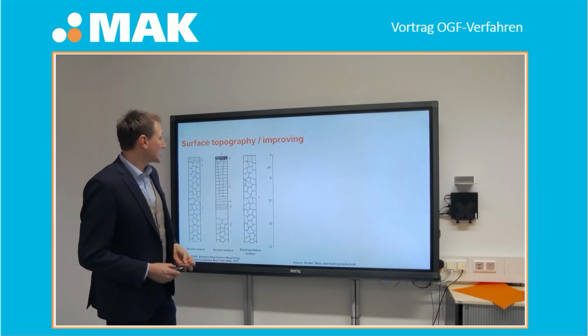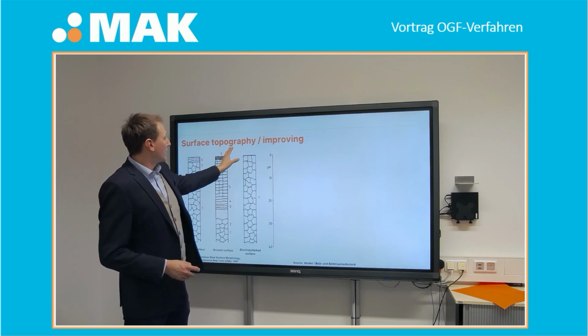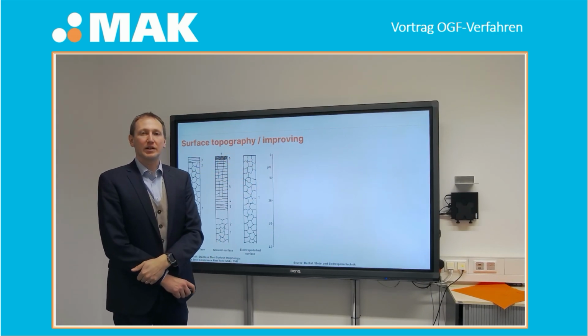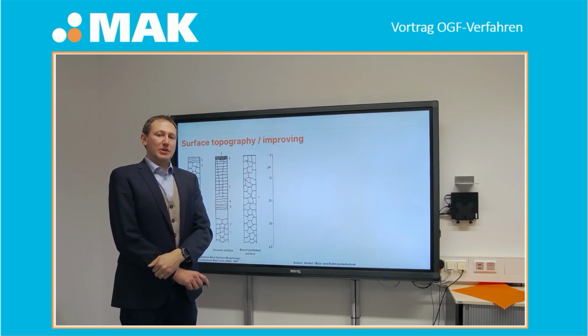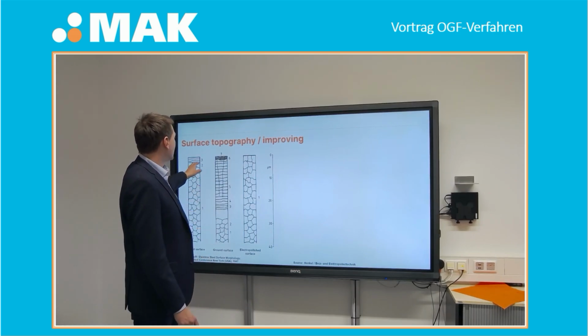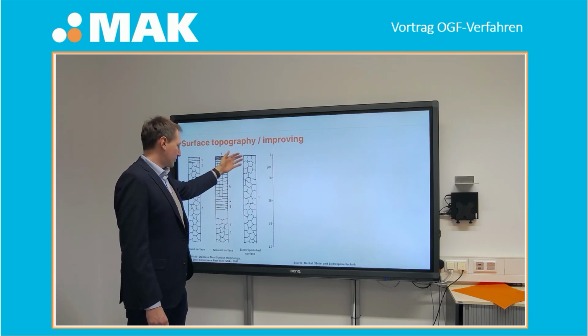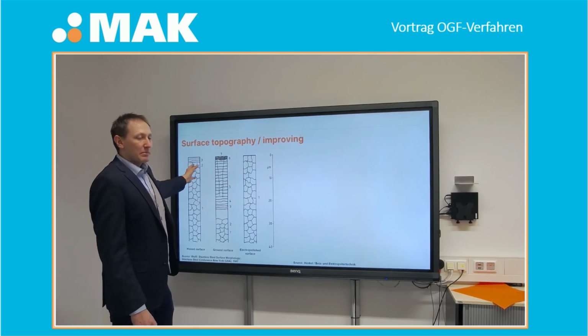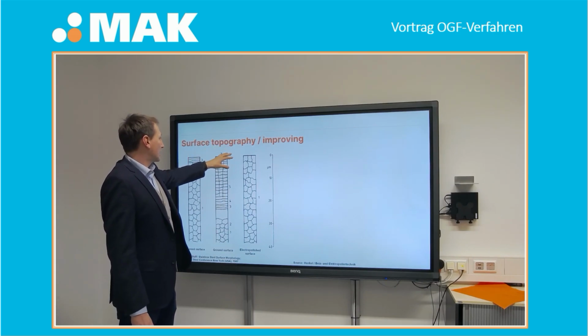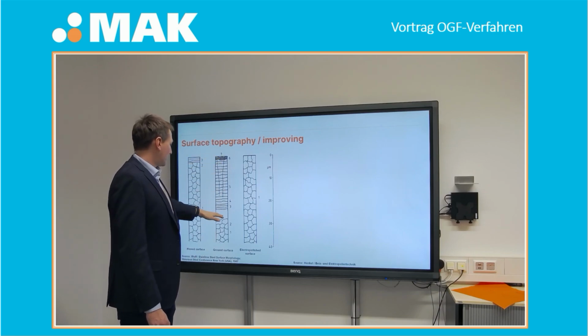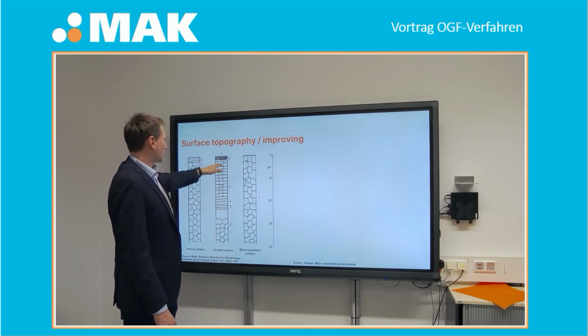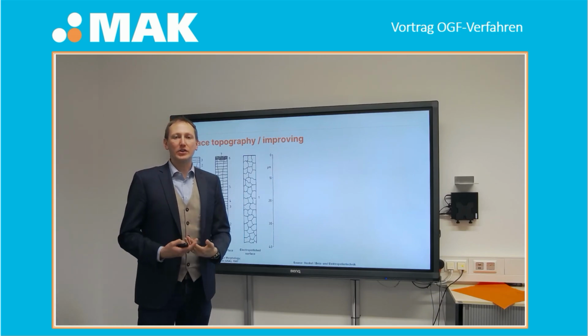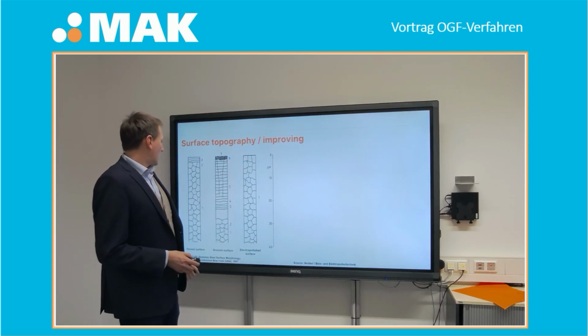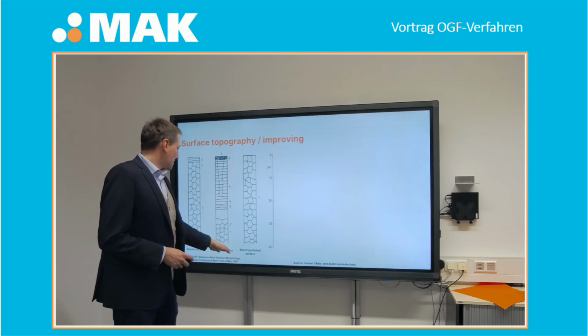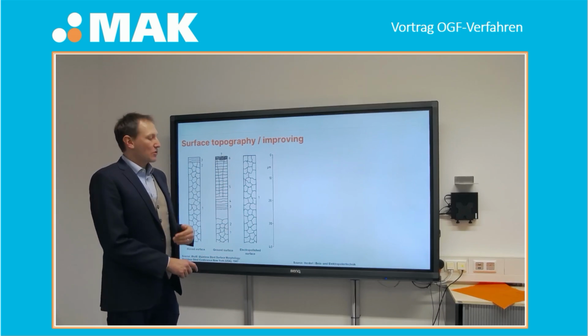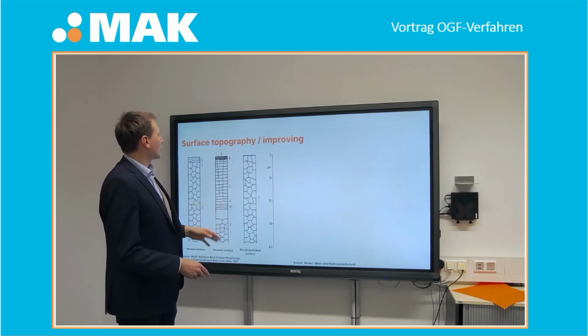Talking about machining, we always have to take into account that by machining a surface of a steel or a material, especially stainless steels, you have an interaction between a tool and your material. The material itself can be influenced by the mechanical machining, and the depth of this influencing factor is influenced by the way you do the machining. Like shown in 1947 by Wolf, we have this so-called Beilby layer,